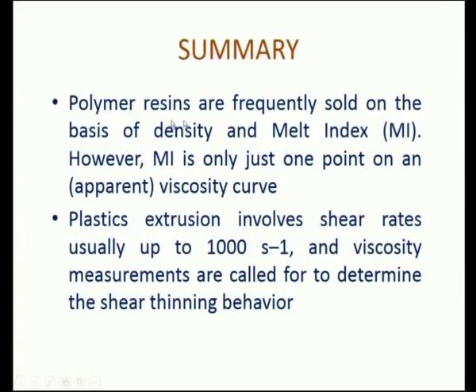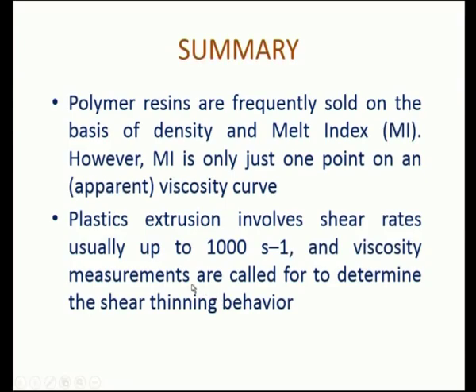These polymeric resins are frequently sold in the market on the basis of their density and melt flow index value. However, the melt flow index is just one point on a viscosity curve, which is the apparent viscosity. Plastic extrusion also involves shear rates usually up to 1000 per second, and viscosity measurements are called for to determine the shear thinning behavior. Shear thinning is a typical case with respect to polymeric systems, because all polymeric systems exhibit pseudoplastic behavior. In pseudoplastic behavior, with an increase in the shear rate, the viscosity goes down, which is shear thinning.